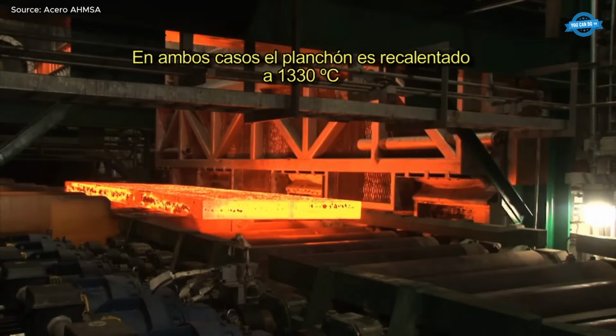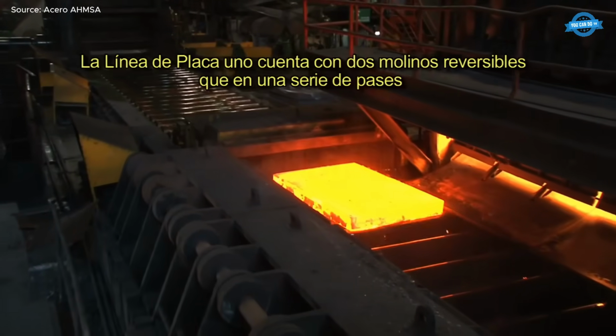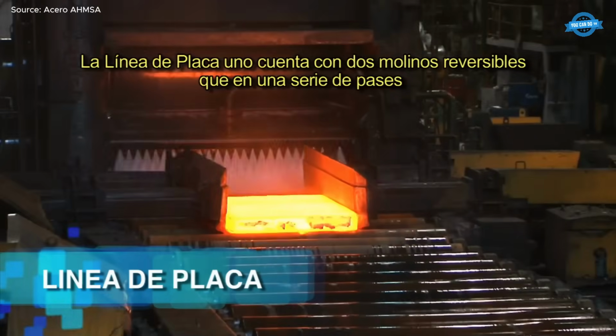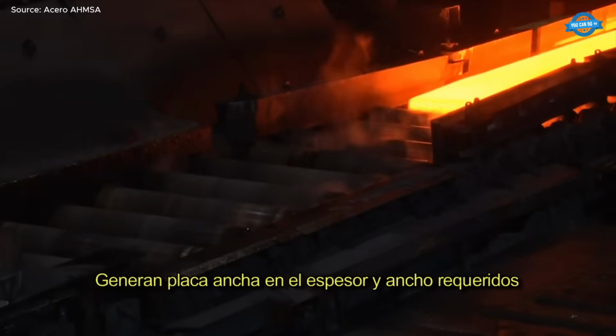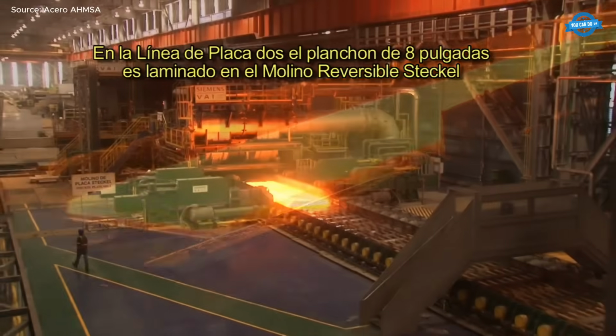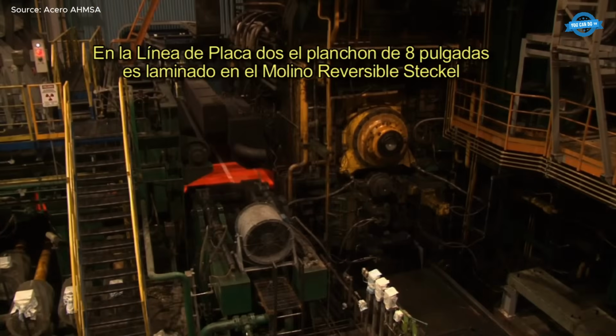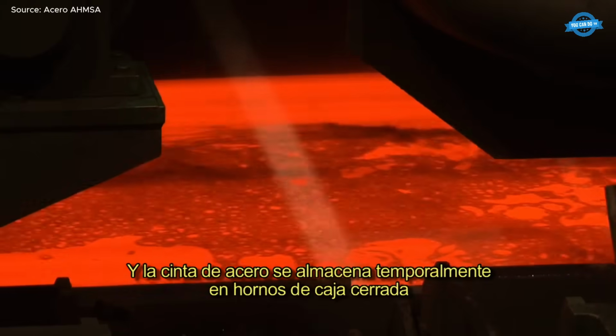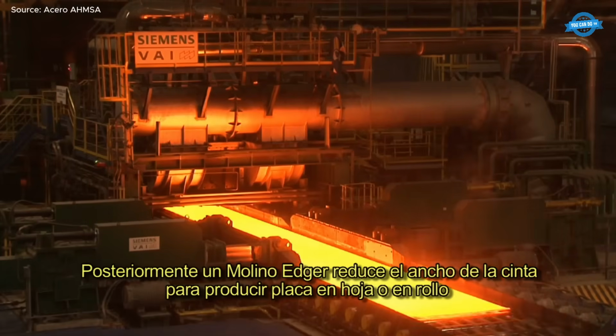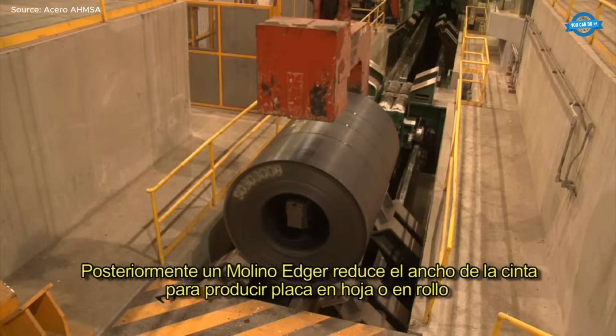Liquid steel is cast into slabs via continuous casting, then hot-rolled into coil or plate. Reheating to 1,300 degrees Celsius, slabs pass through reversing or Steckel mills, then cooled and coiled. For higher strength and surface quality, the coils may undergo cold rolling, acid pickling, annealing, and temper rolling.